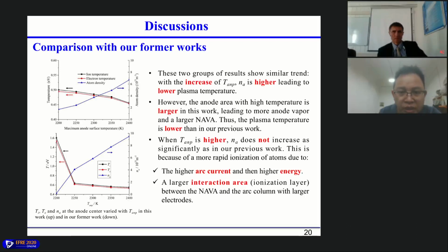This is because of a more rapid ionization of atoms, which is due to, first, a high current and then higher energy, and a larger interaction area ionization layer between the anode vapor and the arc column with the larger electrodes.